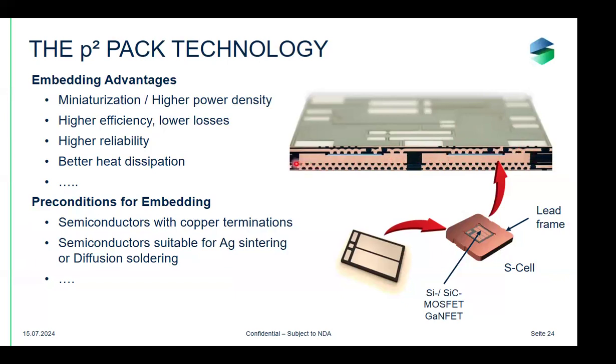What you see at the bottom is 2 levels of copper-filled blind vias. And in this construction, they are used to minimize the thermal resistance from the device through the lead frame to the outside of the PCB. And by doing this, you can create a thermal resistance as low as 0.2 kelvins per watt per cell.